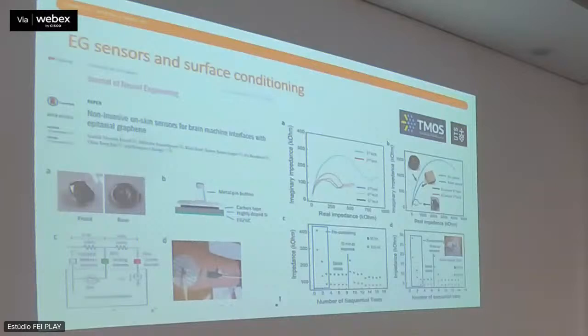Now, very tricky, and I can tell you if any of you are interested, but we are able to make the system completely conductive, and it conducts so well. So basically, any signal that we can sense on the top from the graphene can be very well transferred through the back, throughout the silicon. We use highly conductive silicon, and by making a nice backside contact, we can extract it without any other contribution. So it's really, really simple, very thin, and very easy to integrate into a helmet.